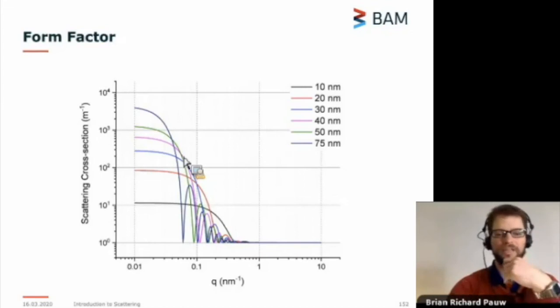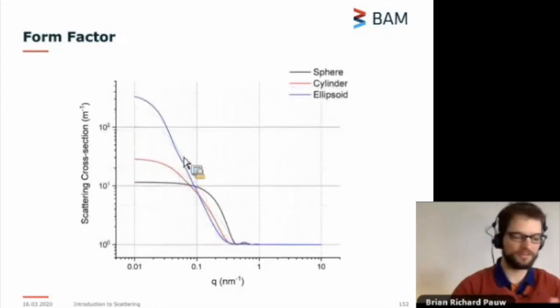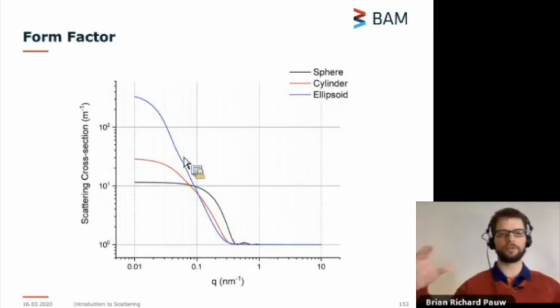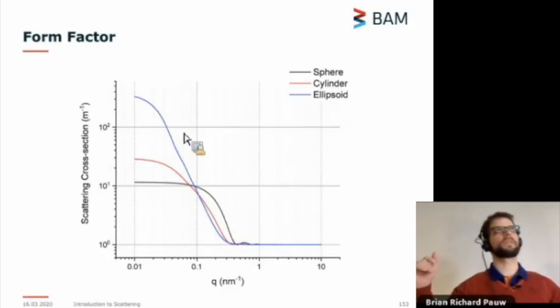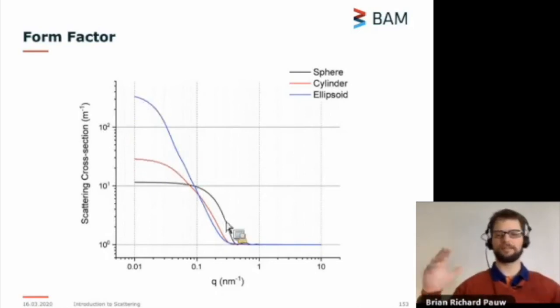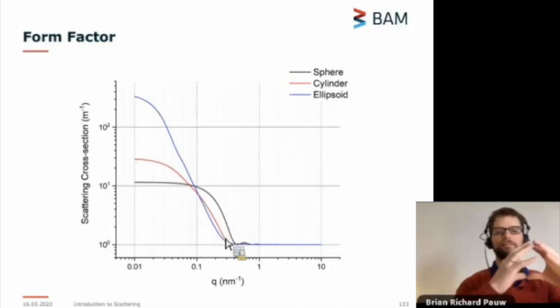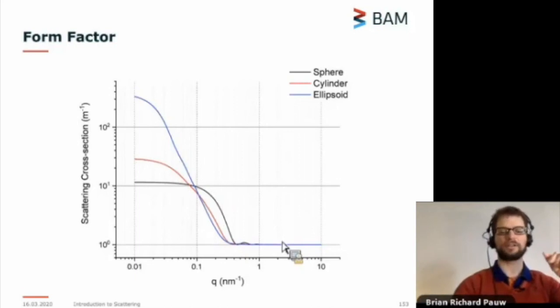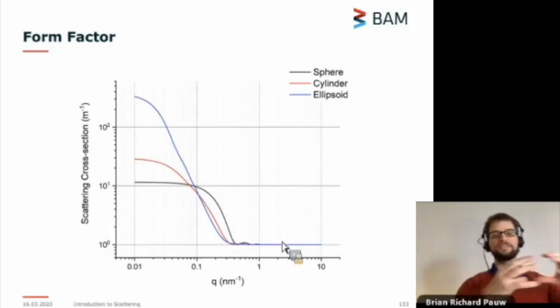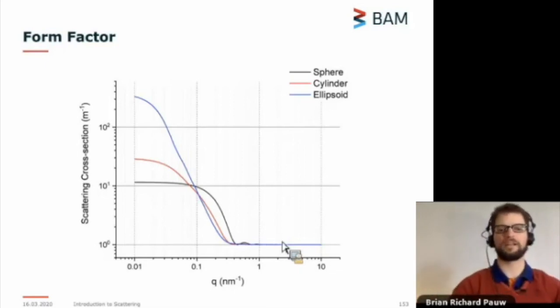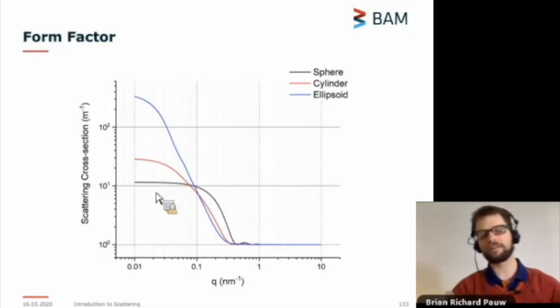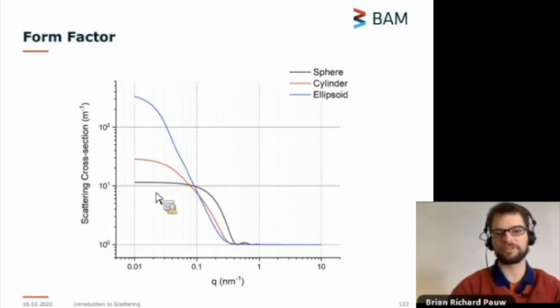It's also dependent on the shape of the particle. So you remember that this scattering is the Fourier transform of the object. It's the pairwise length distribution map. And you can imagine with a sphere that you very quickly end up at lengths which are outside of the object. But with cylinders, you can have some lengths which go on for a longer while. And that's why cylinders look a little bit different, and ellipsoids, depending on whether they're prolate or oblate, can have much different scattering patterns as well.